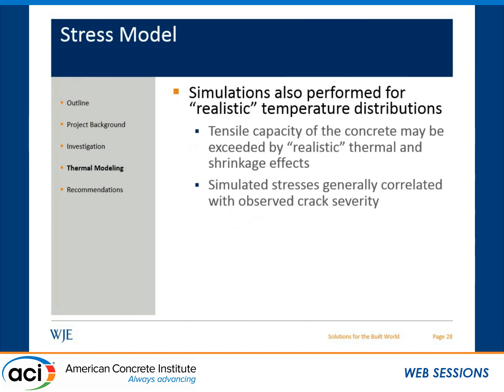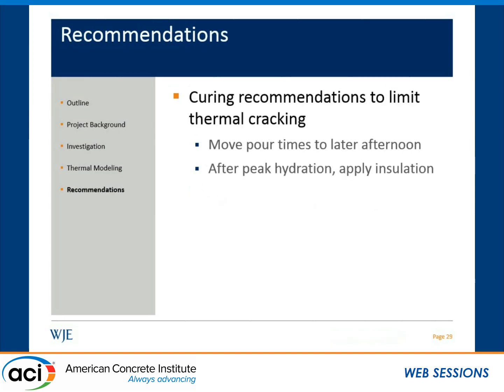So what we found from these simulations was that the tensile capacity of the concrete may actually be exceeded by some realistic thermal and shrinkage effects. The other thing we noted in these simulations was that the stresses that we calculated generally correlated with the observed severity of cracking in the actual bridge decks. So based on our modeling and our field investigation, we proposed a few recommendations to the Montana Department of Transportation.